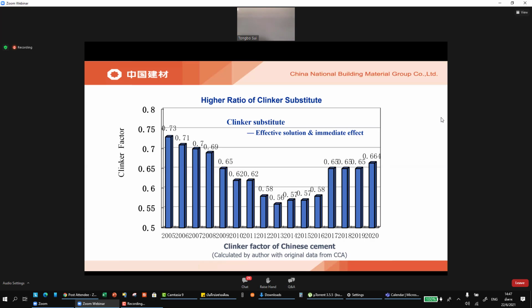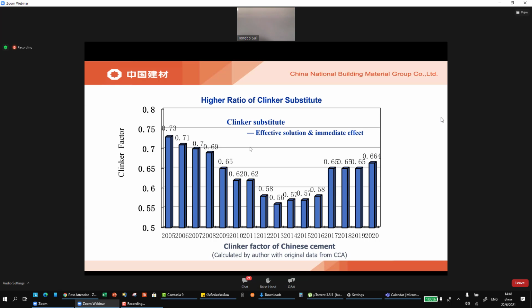Another characteristic of Chinese cement we have seen from the figures is the higher ratio of clinker substitution. We know that clinker substitution can give immediate effect for CO2 emission mitigation. So we have seen the lowest clinker factor of Chinese cement around 2014, and in the recent 3-4 years there's been a little increase of the clinker factor in Chinese cement. But that doesn't mean we use more clinker in the concrete. What we do not use in the cement production, we can also use for concrete. So it's more or less the same effect in terms of CO2 emission per cubic meter of concrete.